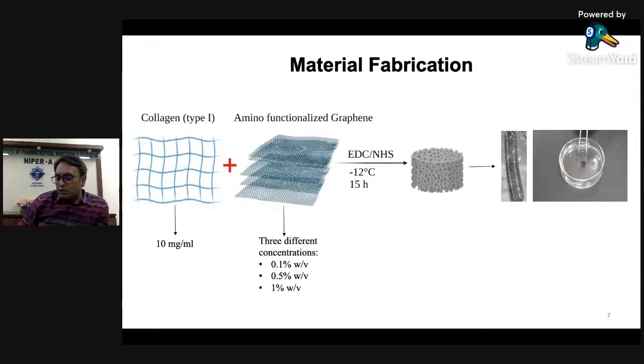For the cross-linking of the material, we have generated amino functionalized groups on the graphene, and then these amino functionalized groups were used as a cross-linker to cross-link collagen. The entire reaction was done in the presence of carbodiimide and N-hydroxysuccinimide at sub-zero temperature.